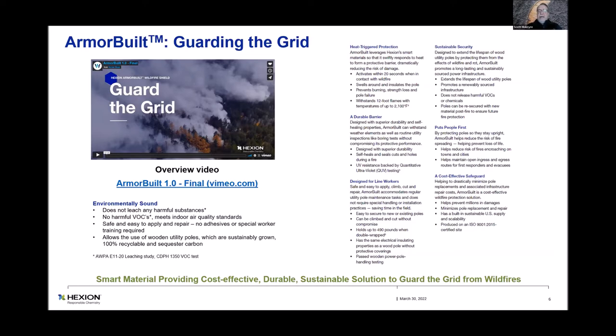It'll withstand temperatures up to 2,100 F. We've done it. Actually, Cal Fire asked us to do a double burn without rewrapping it. And we did a triple burn for them. And it did not char the wood basically at all, less than a 30 second char behind the armor belt. Durable barrier. Certainly designed for linemen and to keep these things from tipping over in fires.